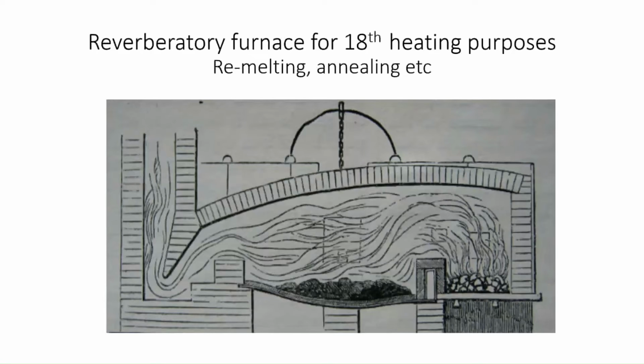If you wanted to heat anything up to a high temperature, whether you wanted to heat charcoal, whether you wanted to melt iron, whether you wanted to use heat for any purpose, annealing, whatever, you used a reverberatory furnace. And it's very simple. Basically, it was just a coke bed on the right, you can see there, with the normal sort of provision of both primary and secondary air. The hot flames went over the roof of the reverberatory furnace and reflected downwards onto the bath or whatever was in there. And then the whole thing was driven by a chimney, which provided the draught.